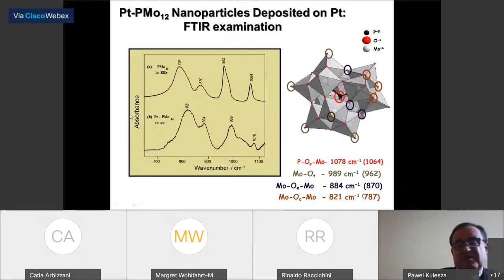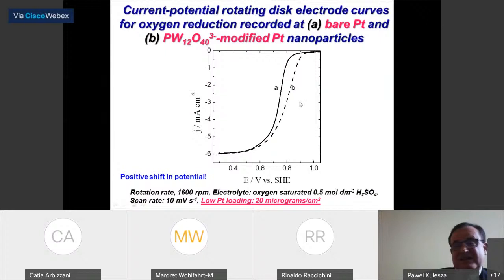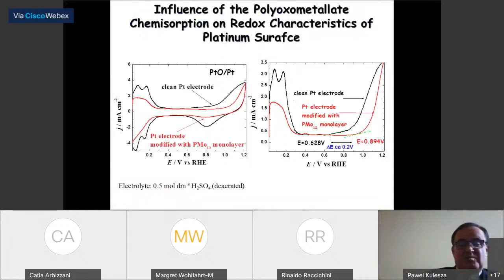I don't need to talk about polyoxometalates, but we can certainly prove the presence on the surface using FTIR. And at that time, we'd say it's nothing special, but it was interesting that modification with polyoxometalate shifted the onset potential. It was very interesting for us. Why? We know now also from XPS that there are electronic changes, but even visually, we see that the oxidation of platinum was shifted toward more positive potential. So in a sense, the potential window of metallic platinum was extended.